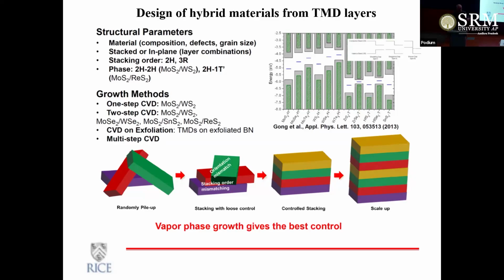Now, when you come to this 2D layers, it's very, very interesting because you can stack them, right? Because they are well bonded in the plane and they are weakly bonded off plane. So you can actually put them together in stacks. So when you think about stacking, it's an interesting problem. It's an interesting engineering approach. The good analogy will be I take two decks of cards and shuffle them, right? And if I have different compositions, I can do the same thing, but each card would be at the atomic scale thickness, right? So by stacking these or shuffling these, I can get these heterostructures with different compositions.